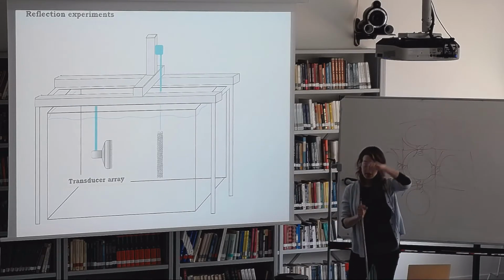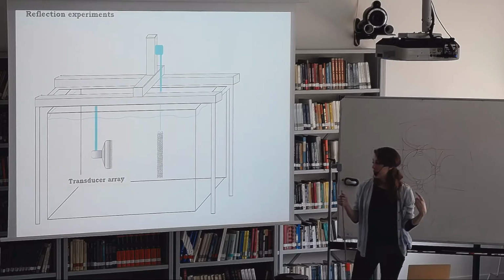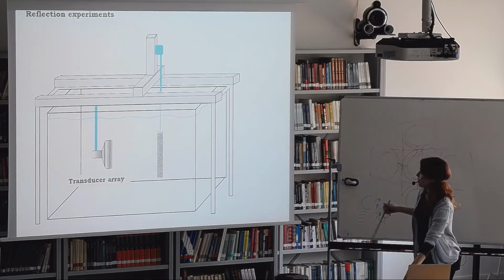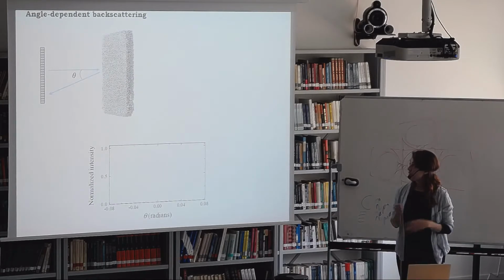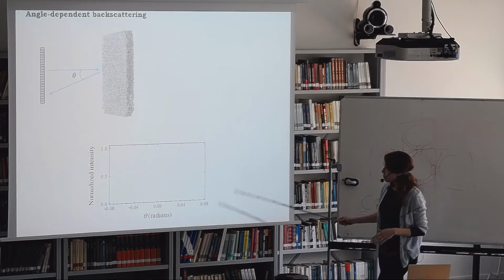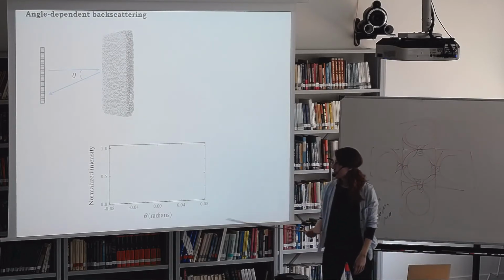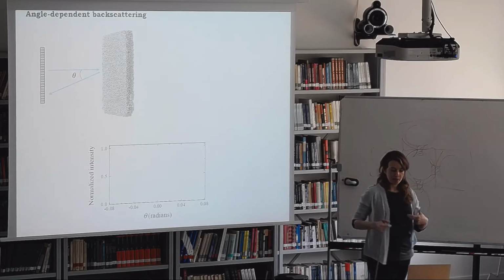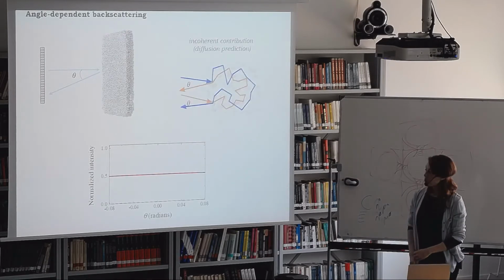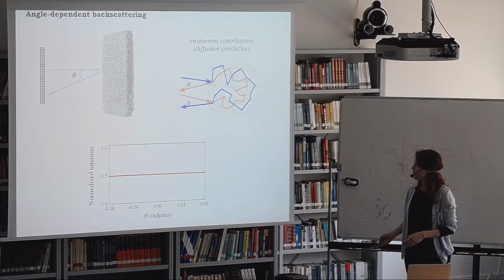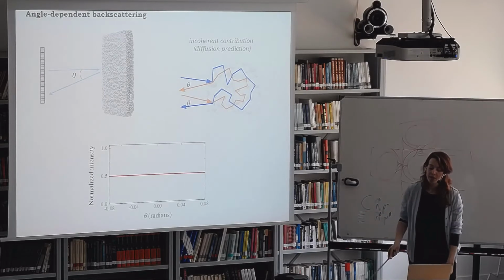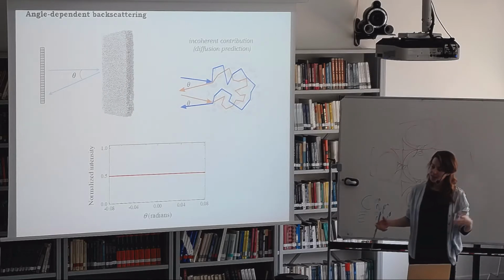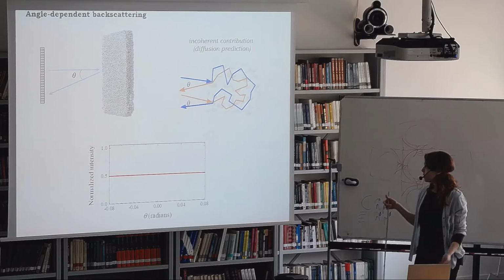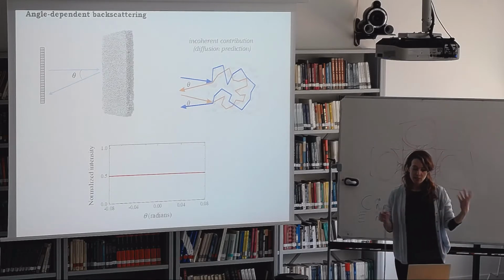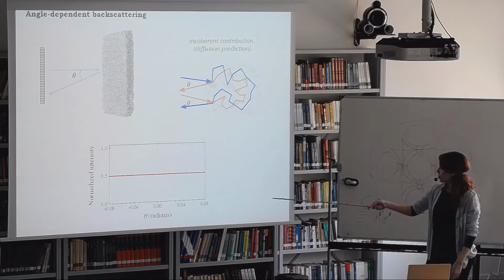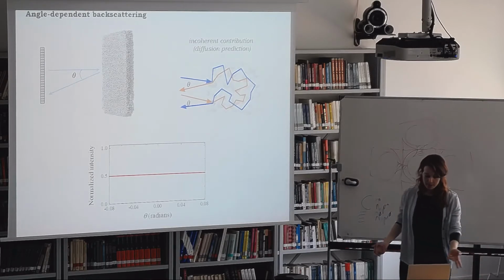This is a collection of tiny transducer elements, which can each emit and receive independently from each other. Using this, we can first measure the angle-dependent backscattering. So we're going to measure the average backscattered intensity as a function of angle between source and receiver. Diffusion theory tells us that we should see nothing really special, just a flat background, because the phase of the waves is randomized by the random position of the scatterers. So if we average over many different configurations of disorder, we're just averaging something random, and we should get a result which really shouldn't depend on the angle between source and receiver.